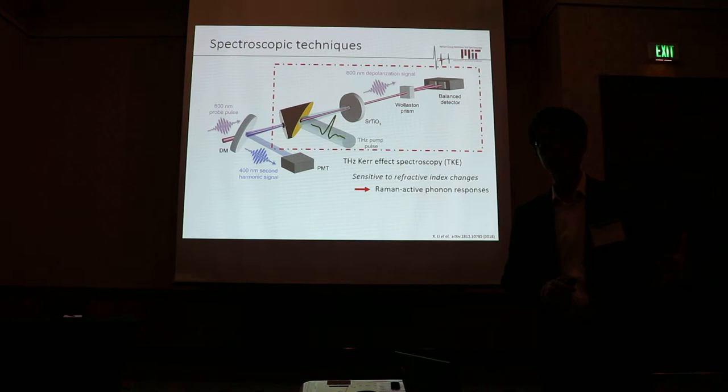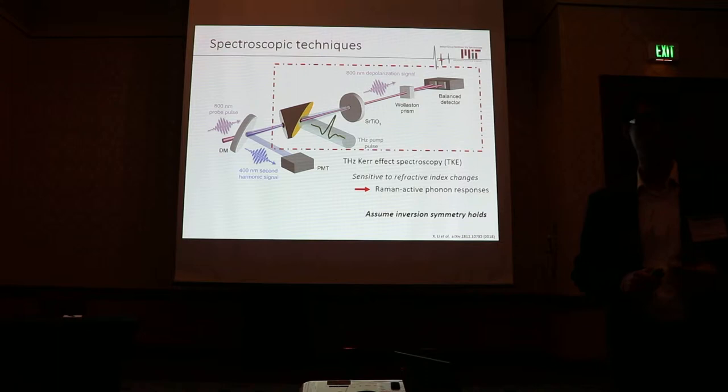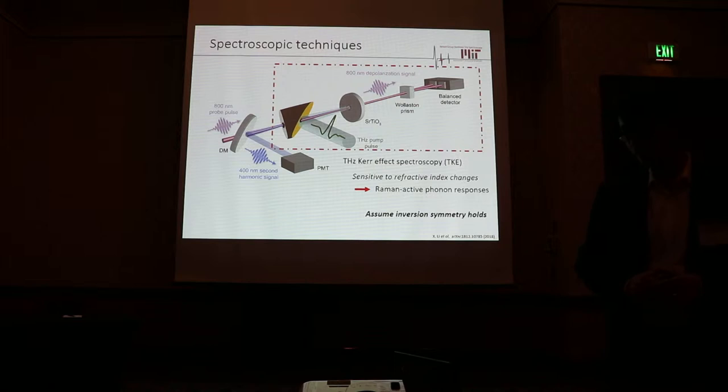The second experiment is terahertz Kerr-effect spectroscopy, in which we detect the terahertz-induced changes in the optical refractive index of the material, such that we detect the Raman-active response. For this to work, we assume that inversion symmetry holds in the material, which is indeed the case for STO, which is quantum paraelectric at equilibrium.